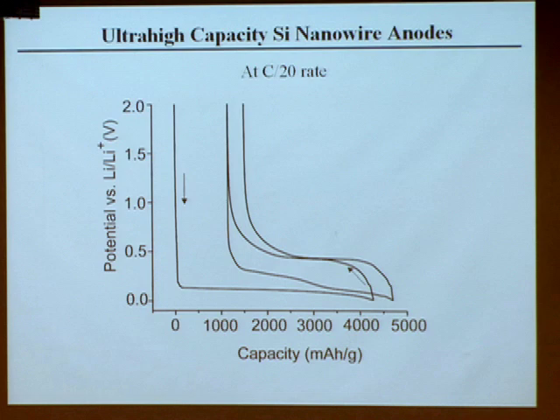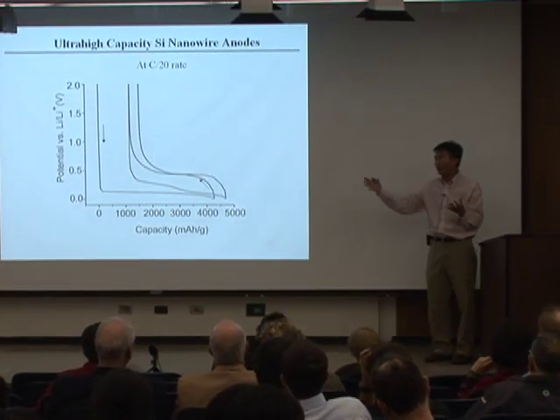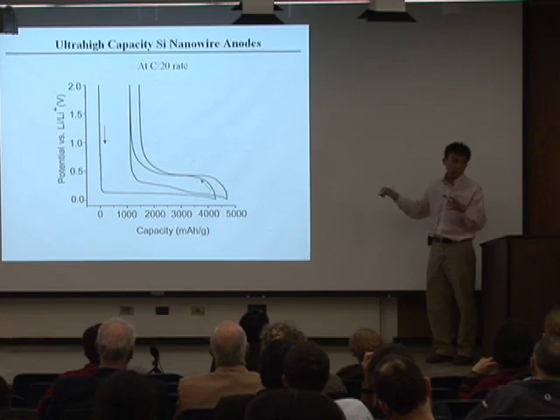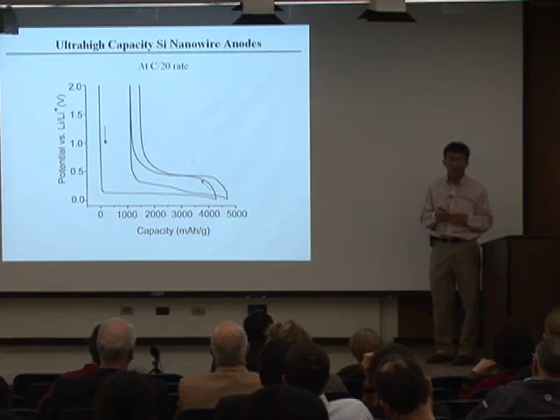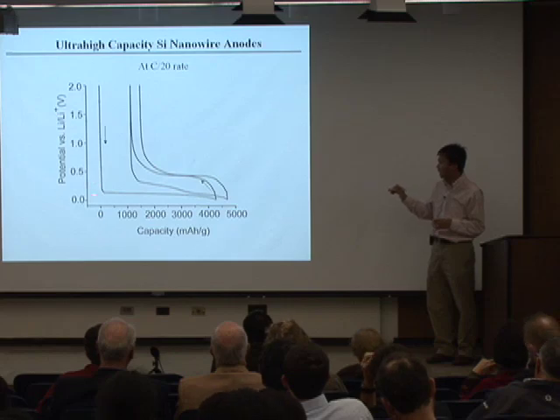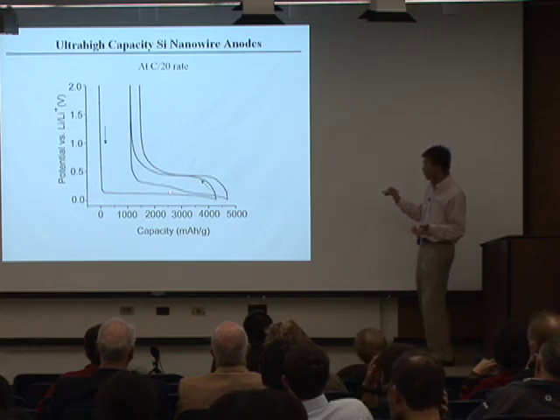This is the potential curve you measure. You monitor the voltage versus capacities. So you give a constant current, you monitor its potential. As soon as you put in lithium ions, the potential drops close to zero. But let me remind you, we are doing this measurement versus lithium metal electrode. So this doesn't mean when you use silicon nanowire for the batteries combined with cathode material, the voltage is zero. If it's zero, you don't gain any energy. This is only half of the cell to allow us to evaluate silicon nanowires.